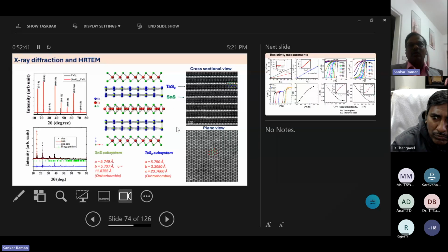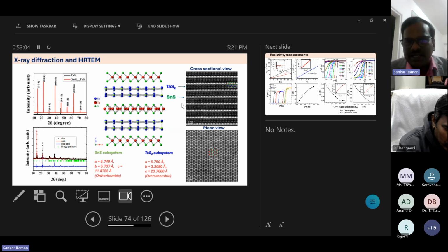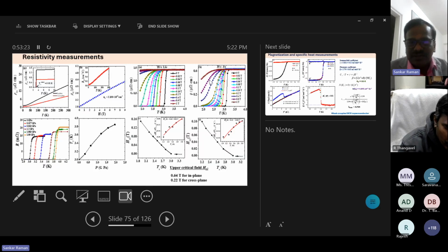Then you can ask me, sir, how are you claiming this belongs to a heterostructure? You can clearly see the X-ray, the black one, with peaks at 15, 30 and 45. There is a periodic XRD. Once you put in the tin sulfide and TaS2, you have a super periodic pattern in between, the red color coming. Also clearly see the TEM. The white one shows the tin sulfide, and the black one has two layers inside, tantalum disulfide. It forms a hexagonal structure, and on top there is an orthorhombic structure. We also confirmed the anisotropy of this material. It's showing 3.1K superconductivity, and you can clearly see the resistance in both directions is totally different.